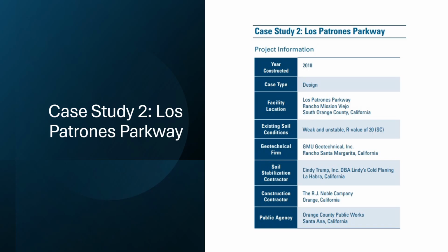The pavement design consisted of 0.2 feet of hot mix asphalt, 0.6 feet of warm mix asphalt, 0.5 feet of aggregate base, and 0.95 feet of cement soil stabilized material. When comparing with the initial pavement design of full depth asphalt, the cost savings from utilizing cement soil stabilization were estimated to be between 30 and 40%. The project required strengths of 300 psi at 7 days, and this consideration provided a 4% application rate of cement.